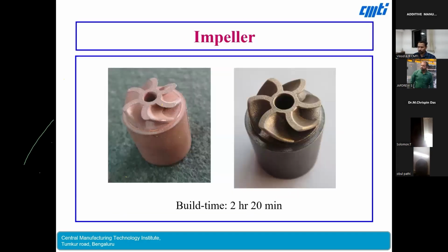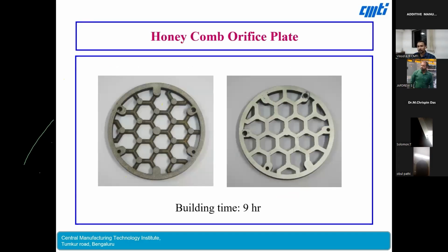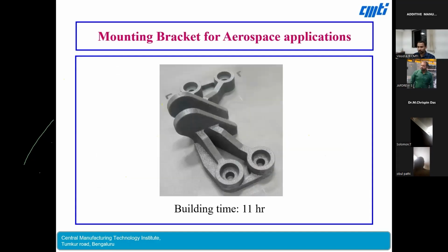You can see 4 or 5-axis components also can be printed within a short lead time, around 2 hours 20 minutes. This impeller was printed. You can see a complex honeycomb. This is an orifice plate, basically for nuclear application for IGCAR Kalpakkam. It is a honeycomb shaped orifice plate to control liquid sodium. At the bottom it is flat, and on top you have a curved face. This was quite difficult to manufacture by conventional process, and it was printed within 9 hours using steel in this process. Like that, you can have different types of mounting brackets for aerospace applications that we have printed.